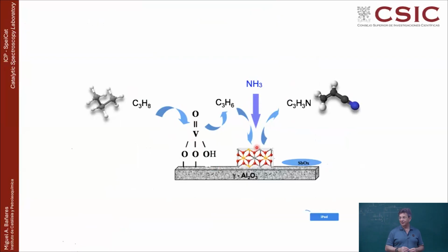It is much lower than that one of vanadium, of propane. But both are vanadium. I mean, the dispersed one, yeah, exactly. Both of them are vanadium, but this is vanadium dispersed on alumina, and the other one is lattice vanadium in vanadium antimonate. So the environment is totally different, because this is vanadium-oxygen-aluminum, the bridging oxygens around it, and the other one is vanadium-oxygen-antimony, because it's vanadium within the antimonate lattice, and the other one is vanadium on alumina. So the nature of the vanadium is very different.